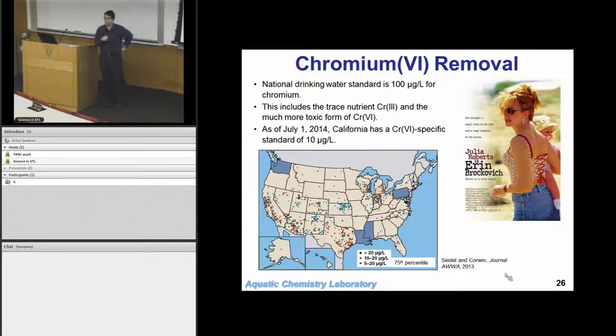It is a carcinogen. In the United States, we have this uncomfortable situation in terms of our regulatory framework where we regulate based on 100 micrograms per liter for chromium. If that's 100 micrograms per liter chromium-3, there's actually not a problem. If it's 100 micrograms per liter chromium-6, it's actually pretty bad. So it's not a very good drinking water standard. And the EPA knows that. And so they have started looking at, should we have a standard that is specific for the toxic form of chromium, the chromium-6? Well, July 1st in California, they now have a chromium-6 specific standard of 10 micrograms per liter. They have a total chromium standard of 50 micrograms per liter, and chromium-6 specific down at 10 micrograms per liter.